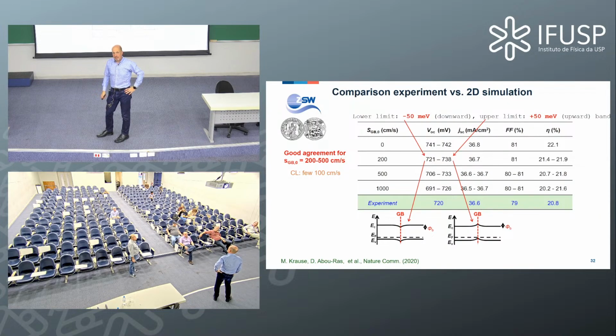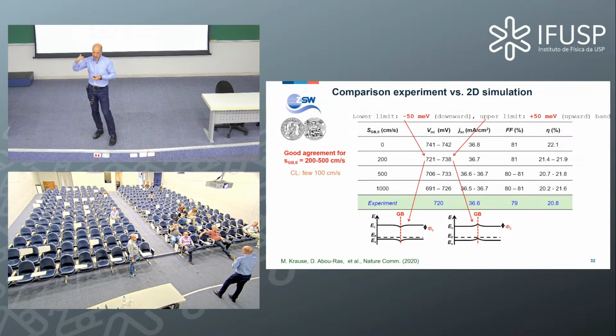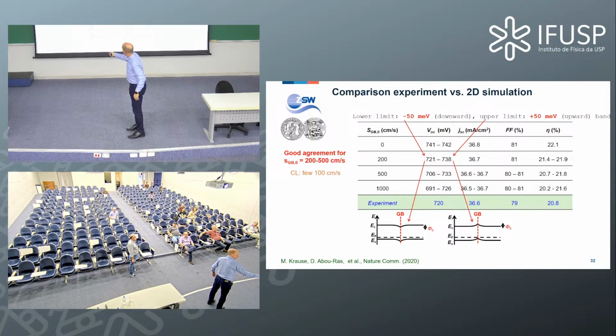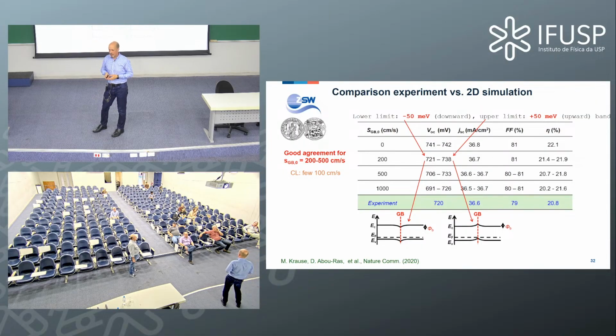And basically, this is the bottom line. You also saw that there is this large variation in the recombination velocity. Then you can see how strongly it changes, because what you have in the end is individual contributions of these recombination velocities on a macroscopic quantity such as the open circuit voltage. There is an impact of the dimension on the device performance. You can simply not so easily simulate the experiment when you use 2 dimensions.